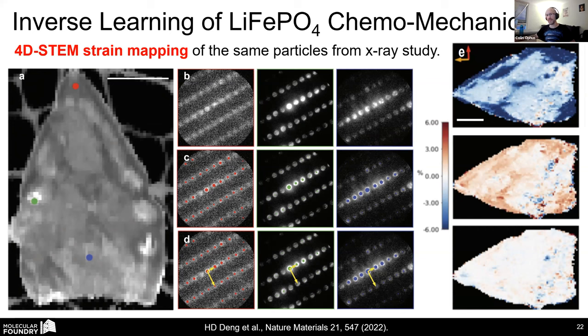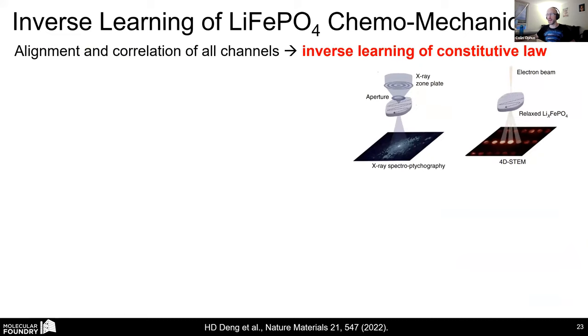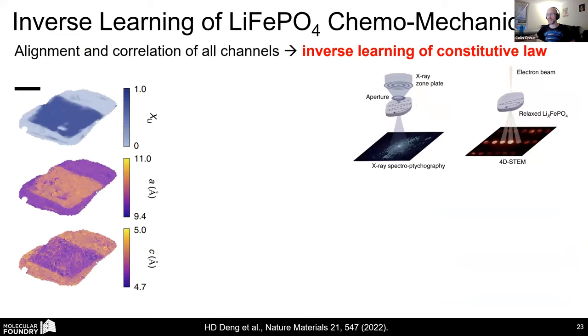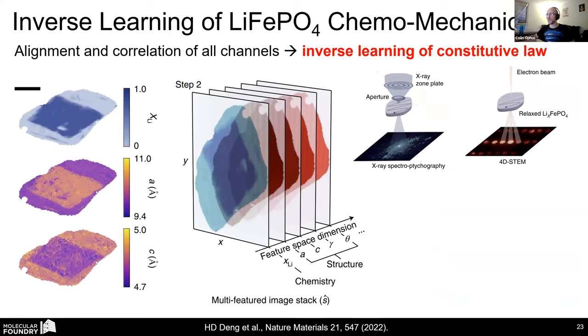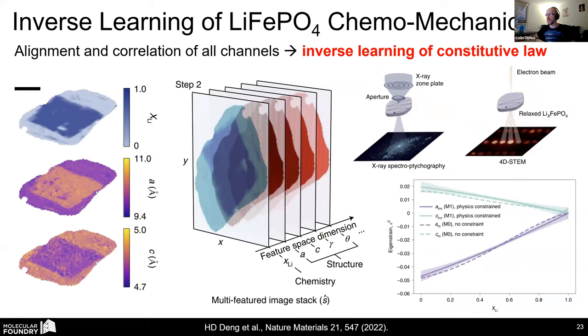And so once we have these data sets, we're scanning pixel by pixel on the exact same particles here, and we can align this data. And then we have a feature space representation of the local lattice constants A and C of this material and the lithium content. And so what we did in this paper is use machine learning techniques to essentially derive the constitutive relationship between composition and strain.